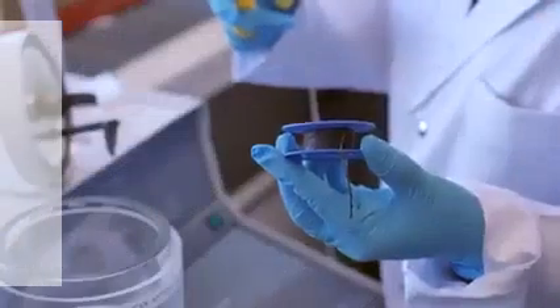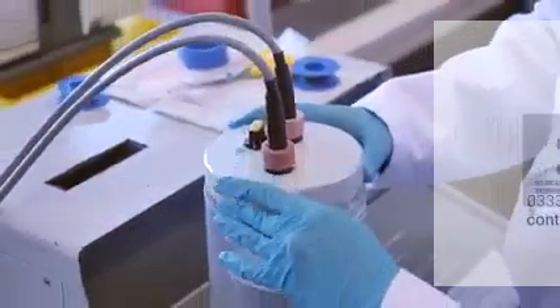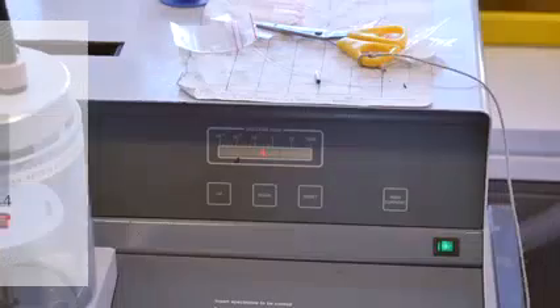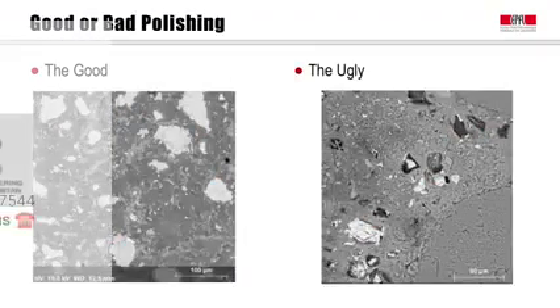Before being used for microscopy, we need to have a conductive layer. Typically, for polished sections of cement, we coat with carbon. We put a piece of carbon thread, then we adjust the height of the sample to get a carbon layer of approximately 10 to 15 nanometers. Finally, we put the sample under vacuum, and we can apply high current to pulverize the carbon on the sample surface. Your sample is finally ready.